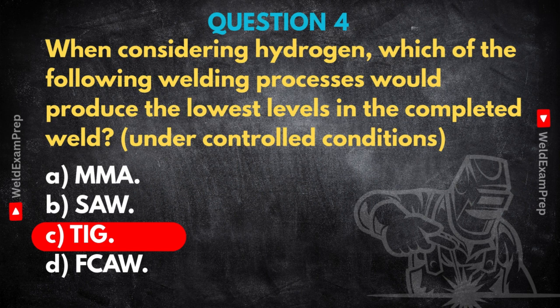I see. And TIG doesn't use flux. Correct. TIG uses a non-consumable tungsten electrode. If filler metal is used, it's a bare wire added separately. The shielding is provided by an inert gas like argon or helium flowing from the torch. So if your shielding gas is dry, your filler wire is clean, and your base metal is clean, then there are very few sources for hydrogen to get into the weld in the first place. It's inherently a low hydrogen process if good practices are followed: clean materials, pure gas.